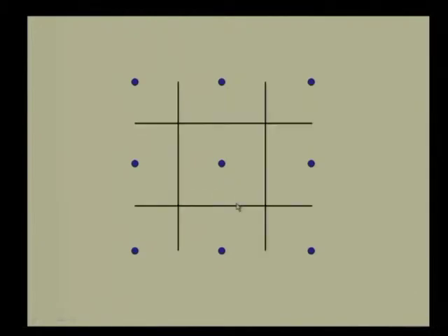In this situation, the nearest neighbors are these 1, 2, 3 and 4. With respect to these nearest neighbors, we can draw vectors to those nearest neighbors and then draw perpendicular bisectors to those vectors. A perpendicular bisector would appear here, there and here. These are lines that perpendicularly bisect the vectors joining this origin to all its immediately neighboring lattice points. That is one set of such bisectors.